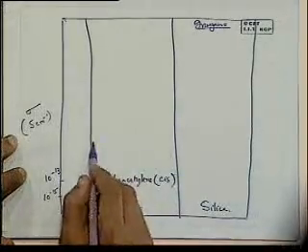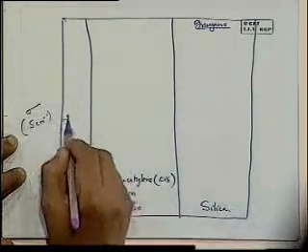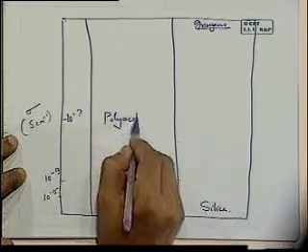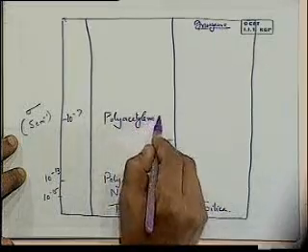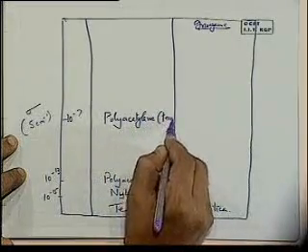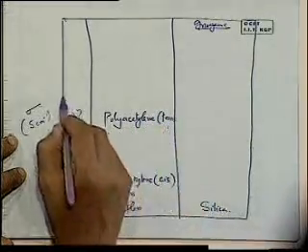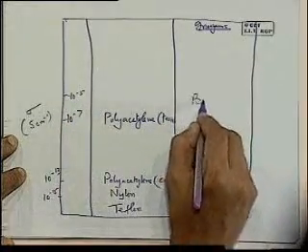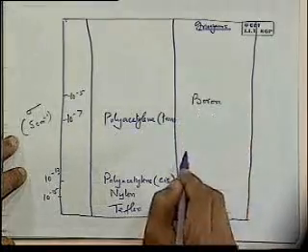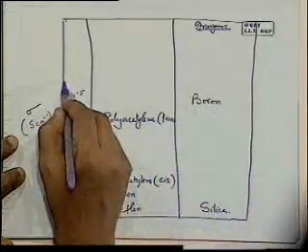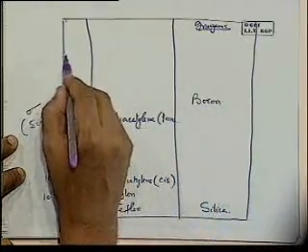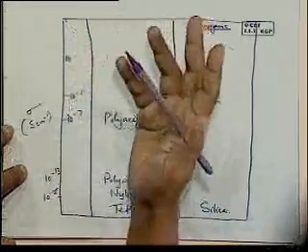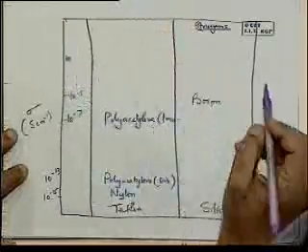And then there's others. We'll come up to about, in the interest of time, 10 to the power minus 7. We've got the other form of polyacetylene called the trans polyacetylene. And then at about 10 to the power minus 5, we've got a material on the inorganic side like boron. Many of the typical semiconductors we're talking of 10 to the power minus 1 to 10 to the power 3, in that 10 to the power 2 range.